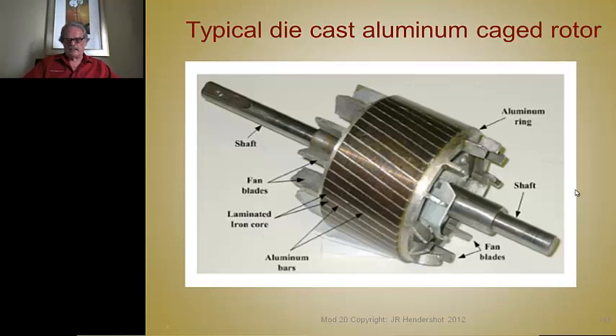Here's what I was referring to. Here's a small single-phase rotor with a die casting in it. You can see the die casting goes down the slot. One thing that's very important here is the accurate stacking of the punchings, so that I have a uniform cross-section for that bar conductor. Remember, I showed in an earlier tutorial a very poorly stacked one. The laminations were so misaligned that in some of the cases along this bar, the lamination completely closed off the passage, so there was either high resistance or